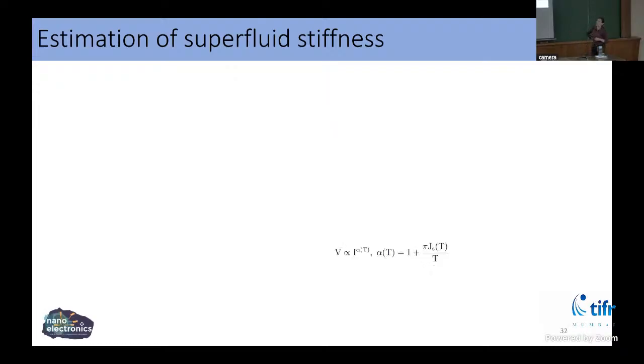Now, usually when we look at IV curves of a superconductor, they are nonlinear. And they are nonlinear connected to this exponent alpha, which is surprisingly related to the superfluid stiffness. Now, there exists something in the 2D limit called the BKT transition, where this alpha has a jump from a value 3 to 1. And similarly, if I put this value back into JS, this also shows a jump. So this value, the JS value, jumping from some non-zero value to a zero value, is known as a BKT transition and is expected to be seen in 2D superconductors.